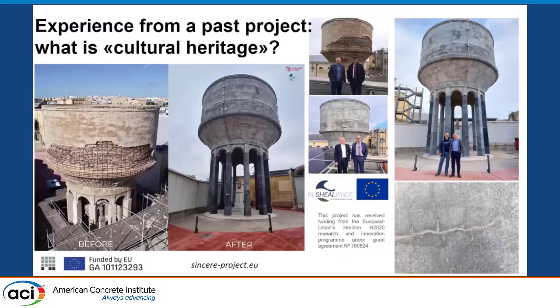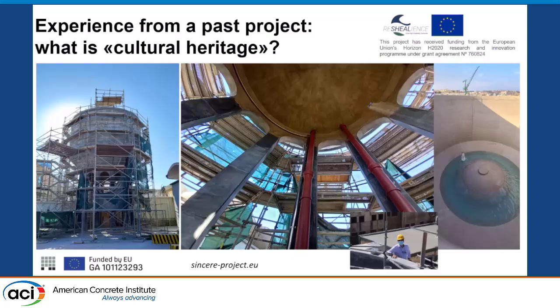Now the structure is in this shape. It's used. We used some self-compacting concrete, so you can see these were some shrinkage cracks which are completely closed. It was a tough experience because, as you can see from this picture, most of the construction work went on in 2021, which was when we were having restrictions due to the pandemic. Most of the work was done in summer, and in summer temperatures can be as high as 50 degrees, so we had to cast overnight. So it was a very interesting experience, and now it's fully used.